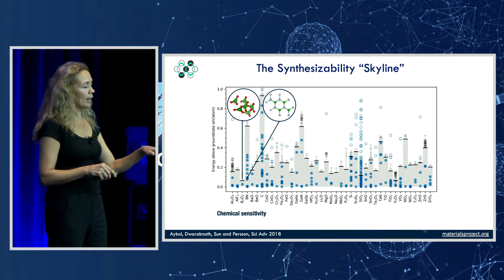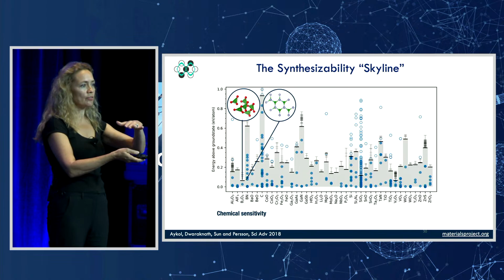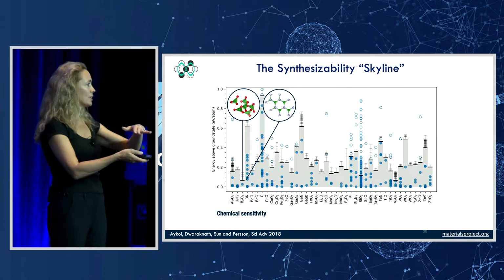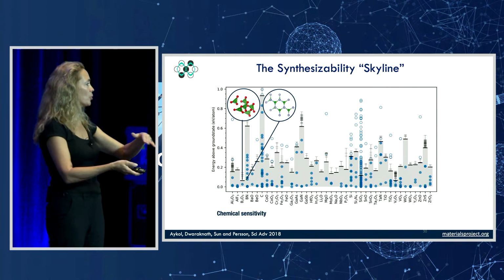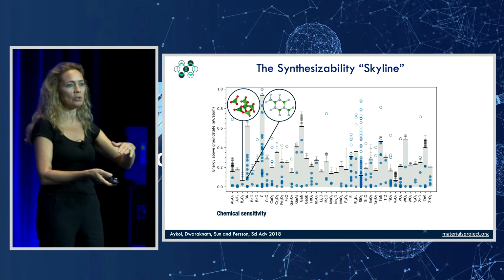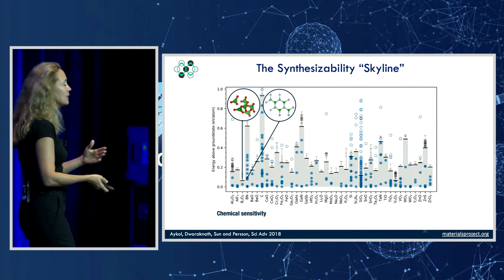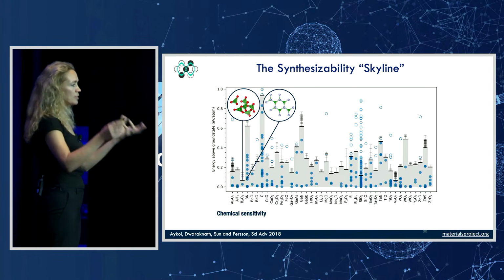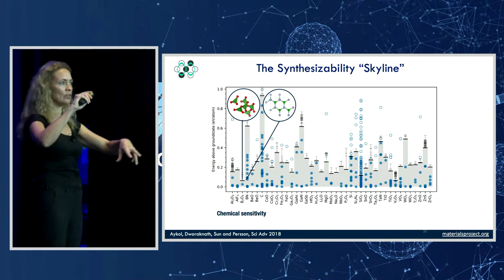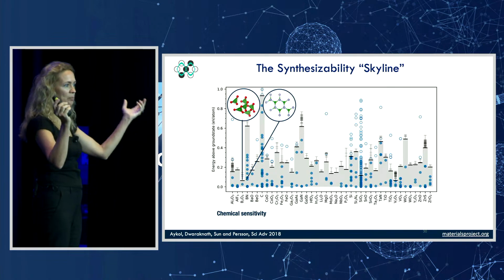That means that you have a low window of metastability, right? Because you can't make that many polymorphs. They all have to be lower than that enthalpy in order to be realizable at any temperature. And it's also set by the fact that boron oxide doesn't really care how these little tetrahedra are organized, right? It's pretty happy being amorphous.